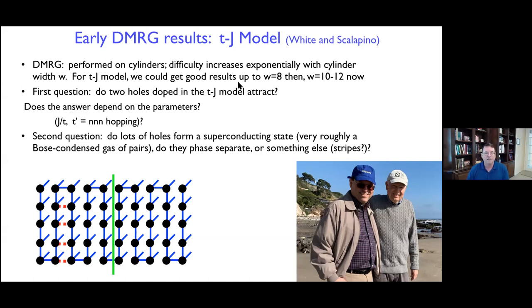For the t-J model, back then, with state-of-the-art computers and techniques, we could get good results up to a width of 8. And nowadays, with better techniques and especially computers, we can go up to width 10 or 12. So the first question is, do two holes doped in the t-J model attract? The idea is that these holes might form Cooper pairs, sort of real-space Cooper pairs. If they bind, then you could think of them as Bose condensing, and that'd be a simple way of thinking about the superconductivity.